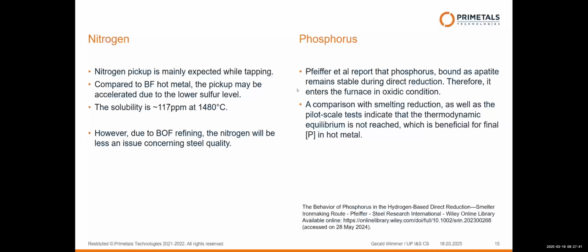But of course, when we do the tapping, classical tapping from the tap holes and then run it into the torpedo cars, we get some contact with ambient air and we will have some pickup of nitrogen during this tapping. The maximum, from a solubility point of view, nitrogen content that this metal can get is about 117 ppm. The purging of the nitrogen in the BOF converter works like it works today for blast furnace. So that's why we expect for the crude steel that we tap from the converter later, we will see similar values for nitrogen as we see today for hot metal coming from the blast furnace.